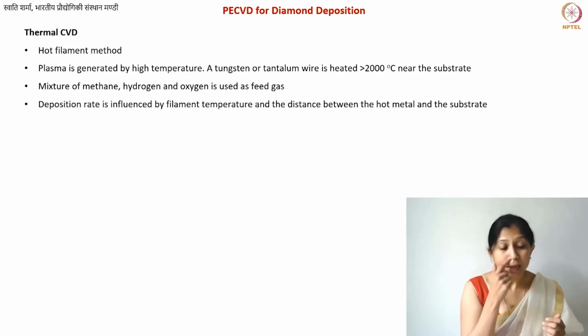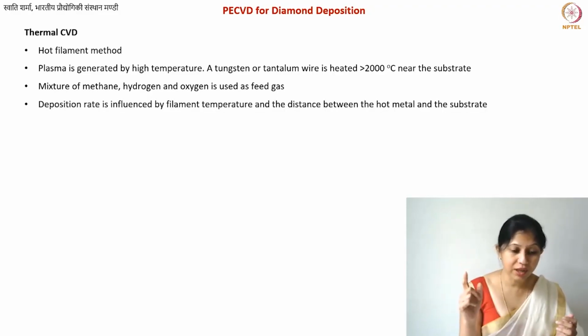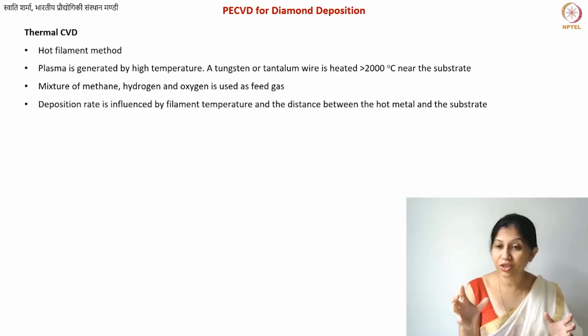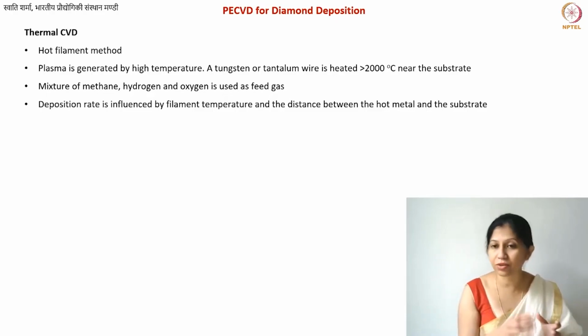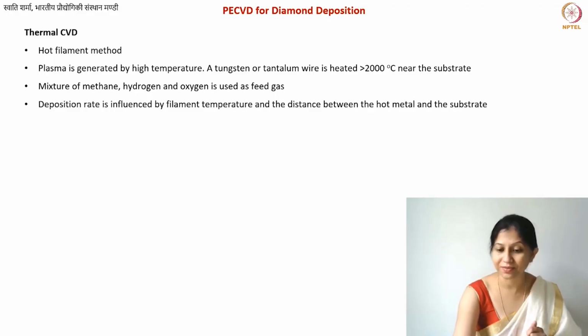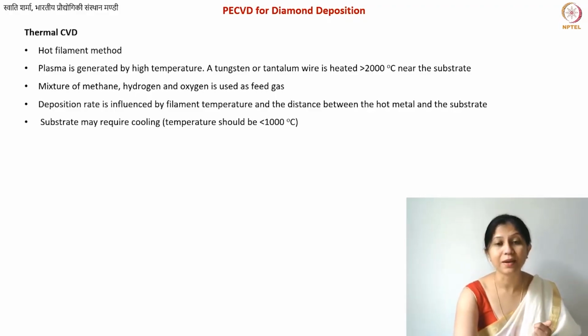Now, in this particular case, one more thing influences the deposition rate. Other things, the substrate temperature and the plasma intensity, are all important. There's one more thing that is important, which is the distance between your hot filament and your substrate. This you also need to optimize, and depending upon the size of the substrate, you may have to change or rotate your substrate. So all of these things you need to optimize.